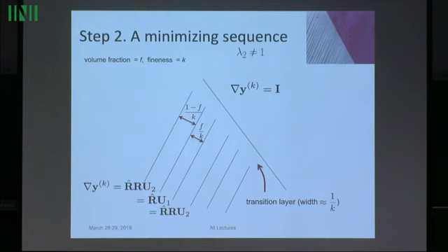And since I've allowed a rigid rotation, this R over here, I just put the gradient equal to the identity here, which models the austenite phase. And you quickly see, I mean, everything here is determined. You quickly see that you cannot have compatibility of the austenite with these individual variants. So I could not just draw a line here and satisfy the compatibility condition.